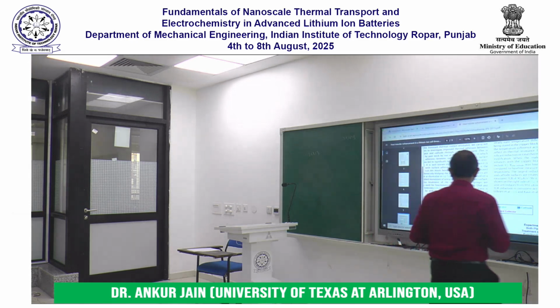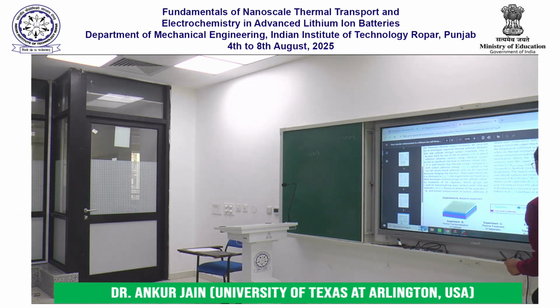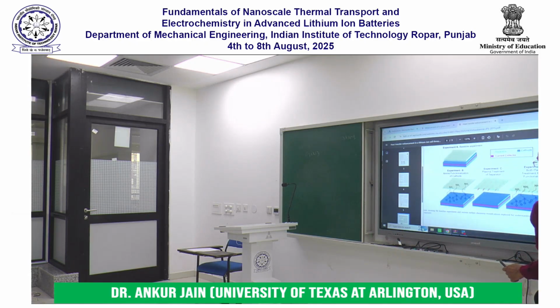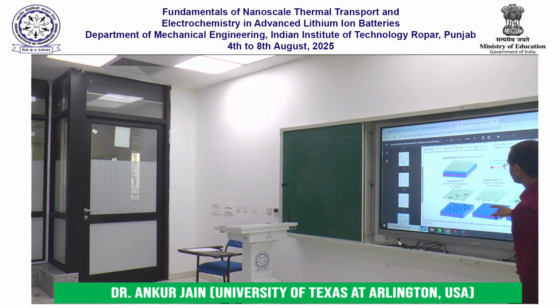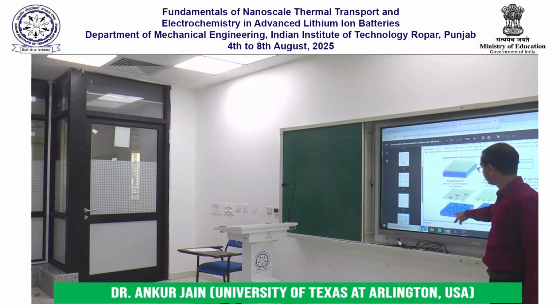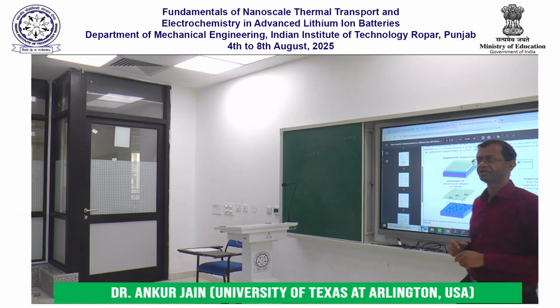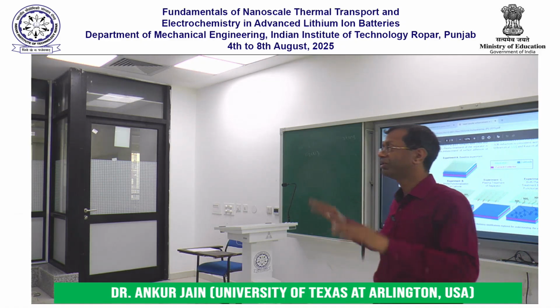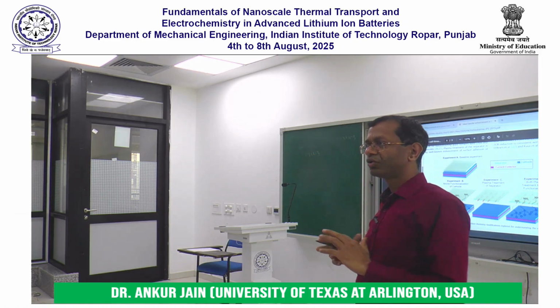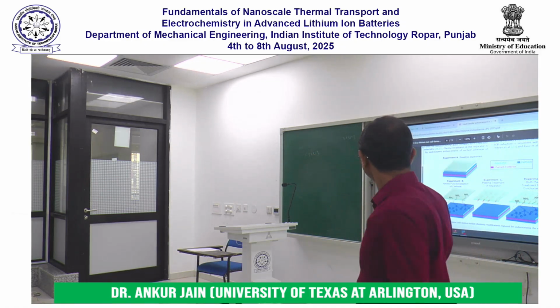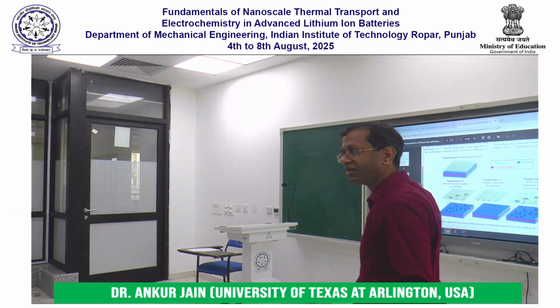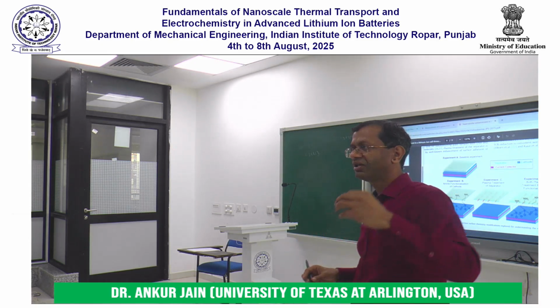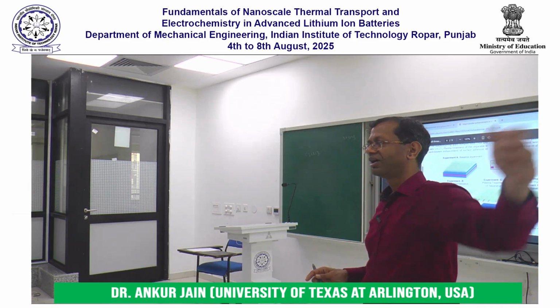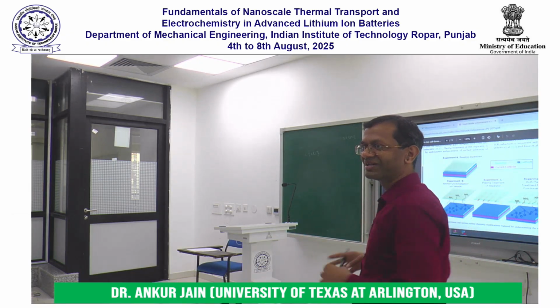So we took our cathode, the blue thing, and we placed the aminosilane molecule on it. Okay, we were doing this completely blind. We took a molecule and an experimental recipe that was primarily developed in the world of biology, and we said, okay, let's try it on lithium ion cells.